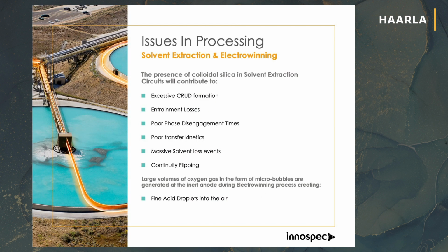So what issues do we have in this processing? You've got crud formation, entrainment losses, poor phase disengagement, the transfer kinetics in the solvent and water system, losses of solvents, and continuity flipping. Then if you go into the electrowinning process, you've got the formation of acid mist, which is a major concern.